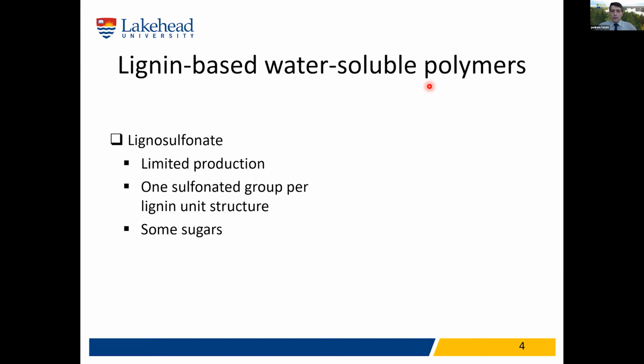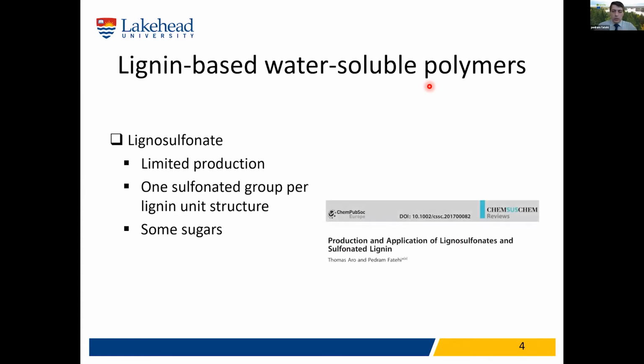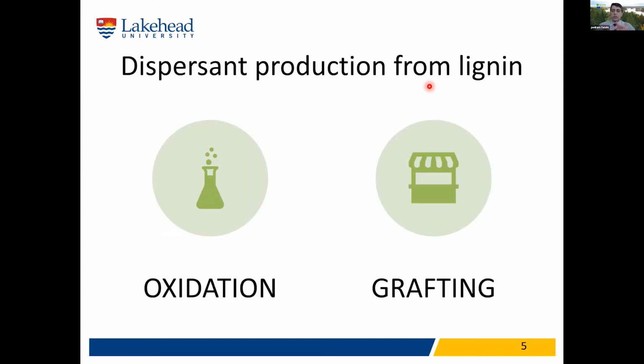But what is available? If you look at the literature, do we have lignin-based dispersant? Yes, lignosulfonate. There are some reports that lignosulfonate was used as a dispersant for some suspensions, but the problem is that the sulfite pulping processes are not dominant, and they are closing one by one. So production is an issue, and we have only one type of sulfonate group on the lignin. So the charge density and the sulfonation degree of lignin for lignosulfonate is limited, and the material you get has some sugar, and that has been problematic for some applications because it's not pure. I discuss all of this in one of the review papers I published. If you are interested, you can look at that.